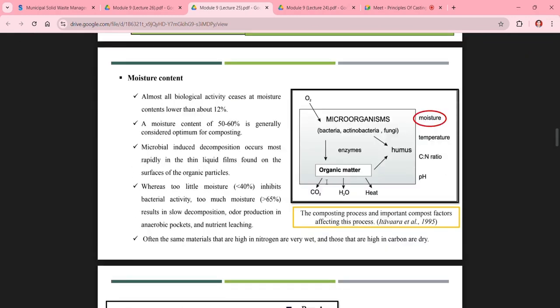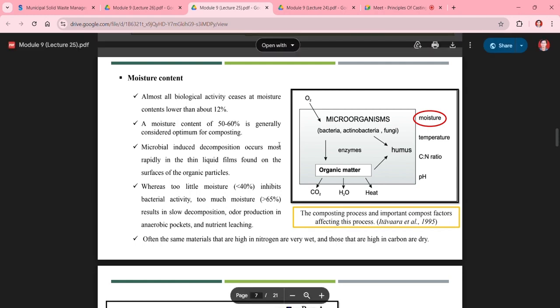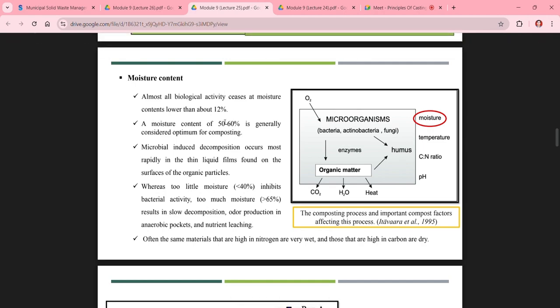Then one of the most important factors to consider during the composting process is the moisture content of the material. The moisture content has to be around 50 to 60% when we are going for composting, because almost all biological activity ceases at moisture content lower than about 12%. If moisture is not there, microbial activity will not happen, and there will be no growth of bacteria and fungi, and these take the major part during the composting process.